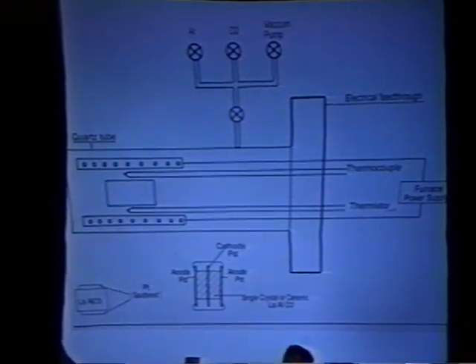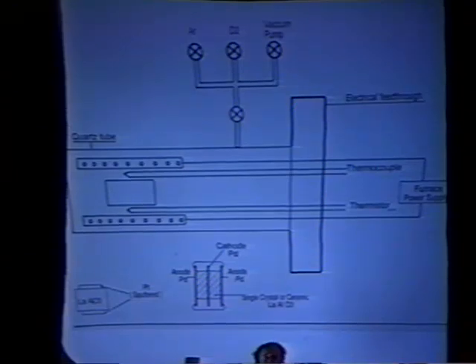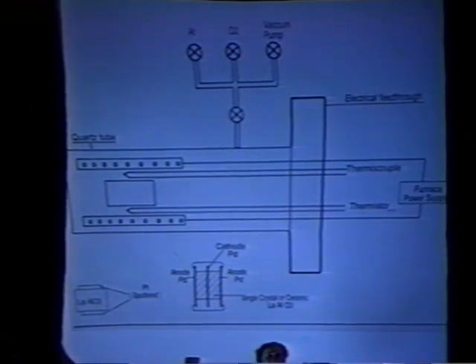So we started with the single crystals. The program started a few years ago with single crystals that were manufactured in the 60s to make solid-state lasers. At that time, they didn't want any vacancies, but in the manufacturing of these single crystals, they ended up having colored crystals. You start with aluminum oxide, which is white, lanthanum oxide, which is white, and you end up with something that's pink or red. In fact, the color comes from the vacancies themselves. Color centers. So we used those crystals for a while and got results that I reported at a conference in Monte Carlo. Since then, we used up all our good crystals, and we ran out of crystals.